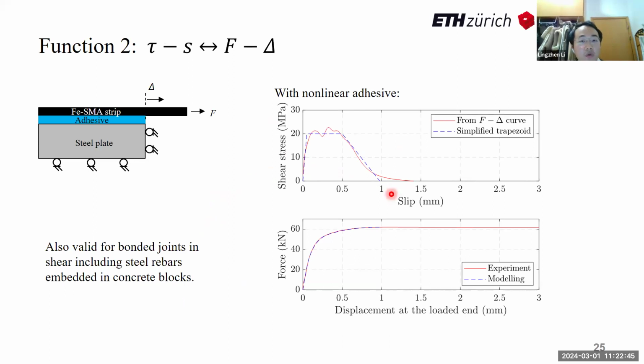The second function is that we could analyze the bond-slip behavior directly from the measured force-displacement behavior. Here I show you an example. During the lap shear test, we could measure the force-displacement behavior as shown in this red curve. Substituting this data in my model, within one shot, we could obtain the local bond-slip behavior shown as this red curve. Or the other way, if we already know the bond-slip behavior in the bond line, we can simplify it to a specific shape for an easier analytical solution. Then we substitute this simplified bond-slip behavior into the inverse of my model. Within one shot again, we could analyze the force-displacement behavior.